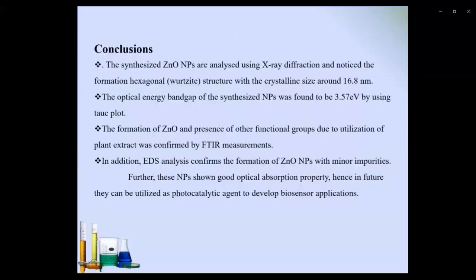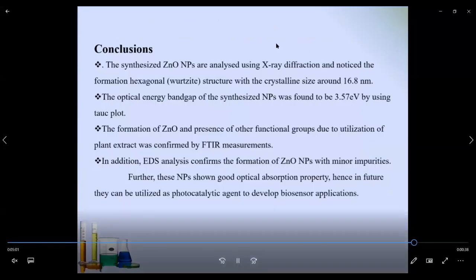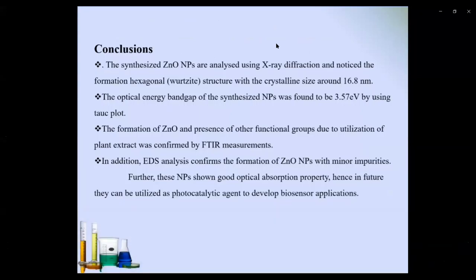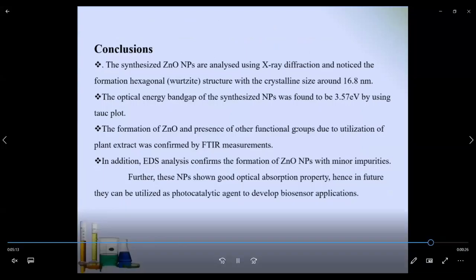With all this result, I would like to conclude that the synthesized nanoparticles are in hexagonal structure with crystalline size 16.8 nanometer. And the optical energy band gap of the synthesized nanoparticles was found to be 3.57 electron volt. And the formation of zinc oxide nanoparticles and the presence of other functional groups was confirmed by FTIR measurements.